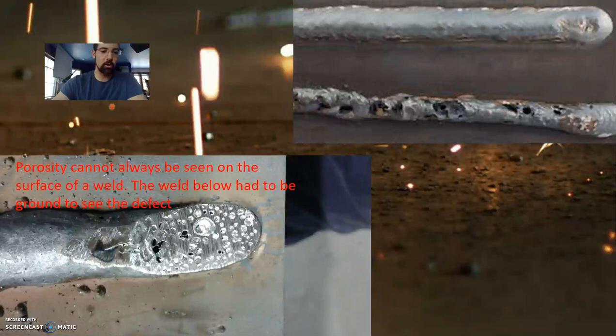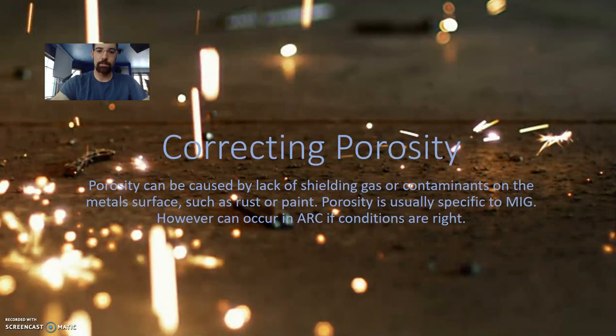Down below, though, you can actually see a weld that looked pretty good from the surface. You can see it all the way to the far left of the weld here. It looks pretty good. But over here to the right side, they actually ground into that weld, and you can see all the bubbles in there. There's going to be no strength to that weld, no consistency. That's why you need to be checking your welds. That's why we use ultrasound to check them inside without grinding them. If you're just practicing, though, grind out your welds, see how you're doing, see if there's any porosity in there. A bend test will also show it.